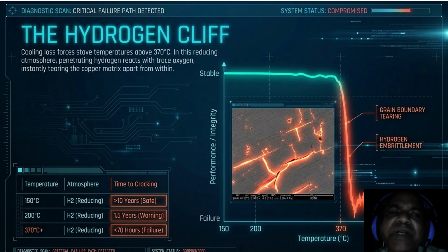In a reducing atmosphere, penetrating hydrogen reacts with trace oxygen instantly, tearing the copper matrix apart from the inside. The micrograph in the center shows the grain boundary tearing. Those bright orange fissures are the physical manifestation of hydrogen embrittlement. Look at the time-to-cracking data at 370 degrees. You have less than 70 hours until total failure. This is not a slow wear process. It is an instantaneous metallurgical death sentence that destroys our cooling capacity and risks a breakout. This brings us to a fundamental paradox in how we select our material. We often choose the purest material for conductivity, but that purity creates its own set of mechanical vulnerabilities.